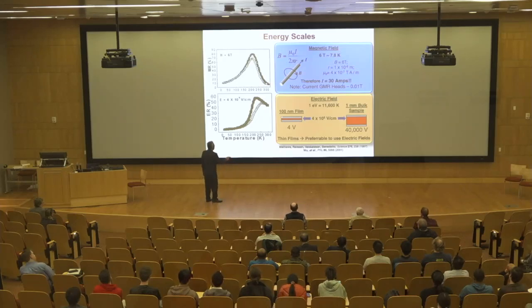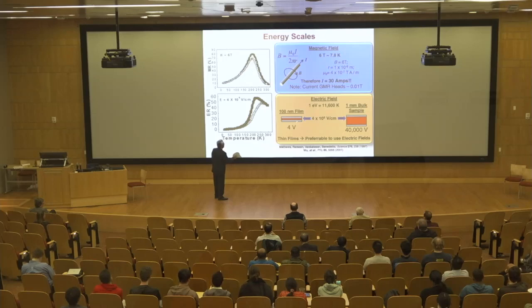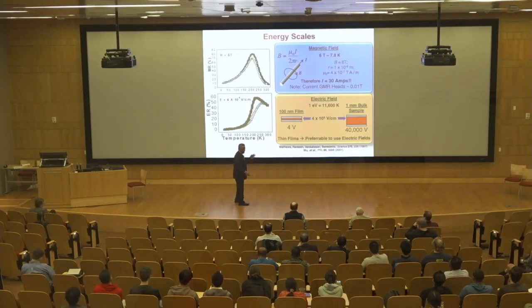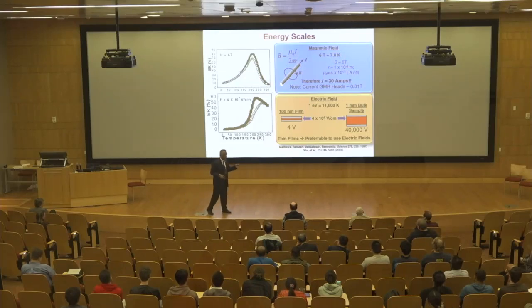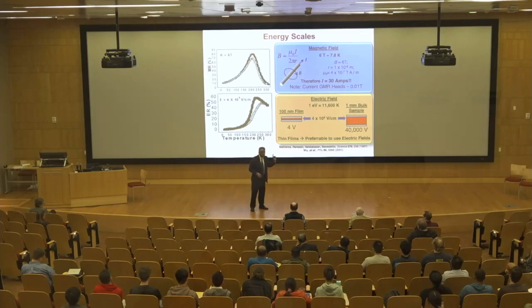The electric field, on the other hand, scales with the dimension. So the electric potential scales with the dimensions. The field is fixed at 400 kilovolts per centimeter. And so if I have a 100 nanometer thick film, it's only 4 volts. If I have a 10 nanometer thick film, it's only 400 millivolts. But if I go to a millimeter substrate, of course, it's 40,000 volts. So the key message was, if I have capacitive devices where electric fields can be very useful, I can reduce the voltage. But if you're an electrical engineer, you say 1/2 CV squared is very important, so I can reduce my energy this way. And this is the primary reason to say, how do I manipulate a magnet with an electric field? That's not the conjugate variable. The magnet would be a magnetic field.